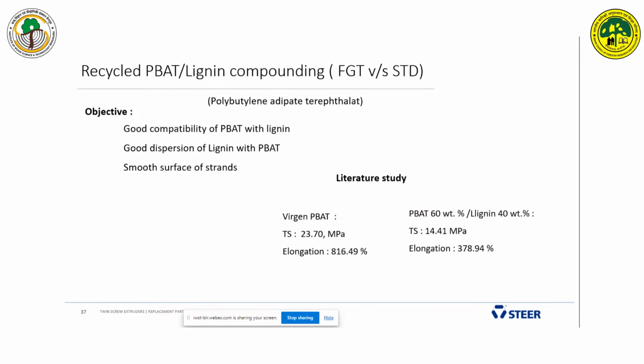Now, when you are comparing the FGT technology and the standard, with the case studies of PBAT lignin, it is a recycled PBAT. It is not a virgin PBAT. We have taken the recycled PBAT and used it again for value addition, adding lignin into it. Our main intention was to incorporate more and more lignin, with better dispersion and also a smooth surface.